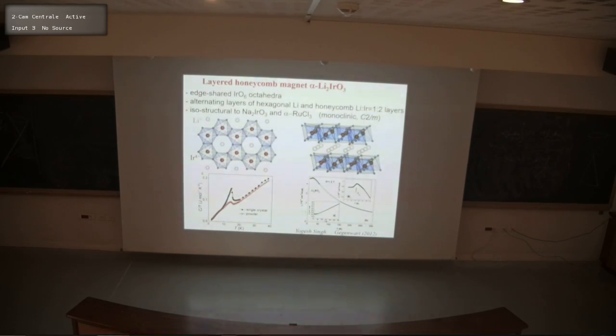So it turns out that all of the materials that we found experimentally so far contain a combination of these terms. Okay? There's no material that contains just the Kitaev term. These other terms are also present, and they help stabilize the magnetic order seen in all of these systems.